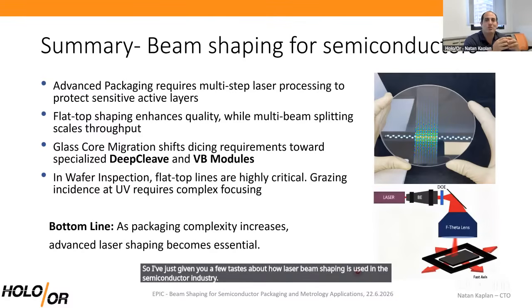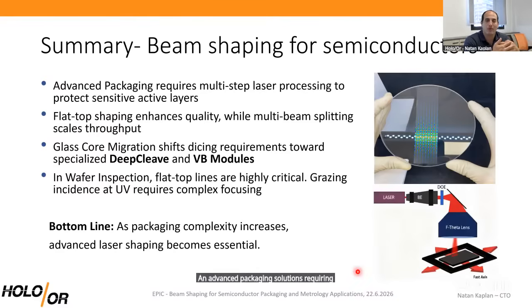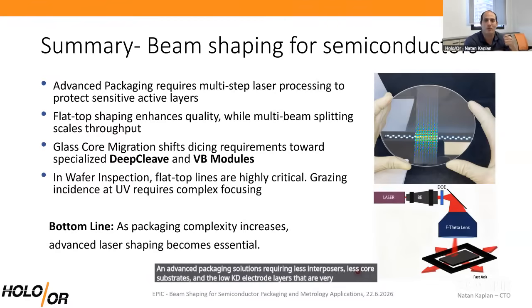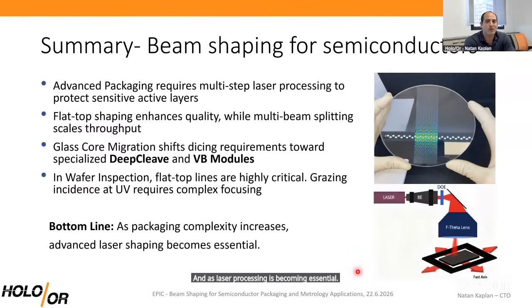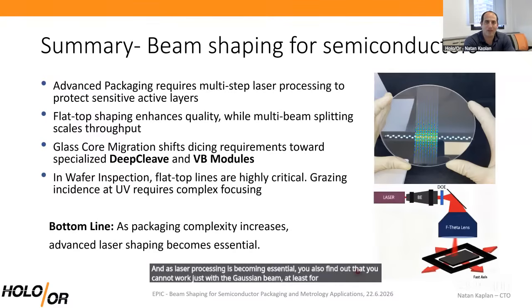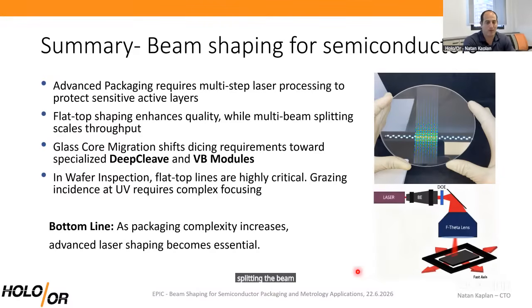Yes, especially with the increase in advanced packaging solutions requiring glass interposers, glass core substrates, and the low-k dielectric layers that are very hard to remove before dicing, laser processing is becoming essential. You basically cannot process these just directly with the saw. And as laser processing is becoming essential, you also find out that you cannot work just with the Gaussian beam, at least for many of these applications. So laser beam shaping plays a pivotal role, both for the quality, which means the yield of the process, and for the throughput by splitting the beam or by allowing for more efficiency in terms of depth cutting.